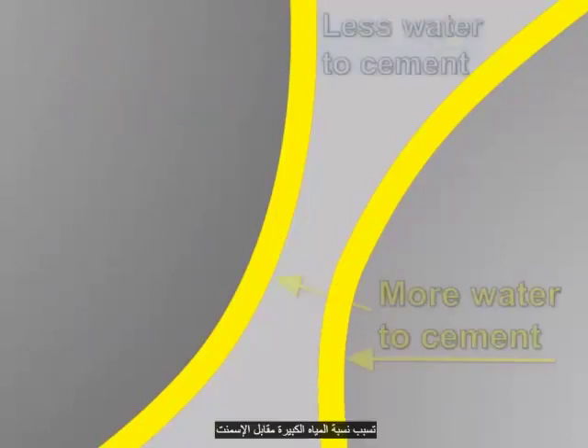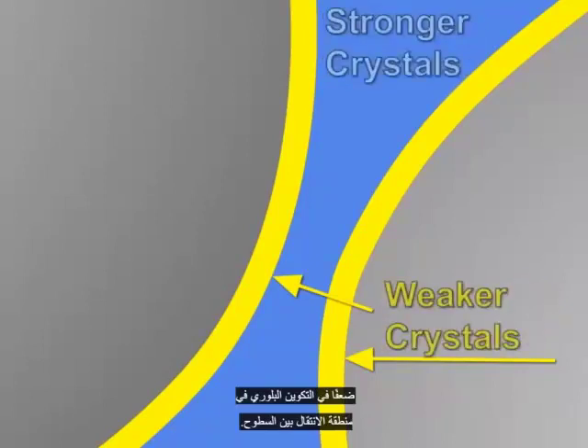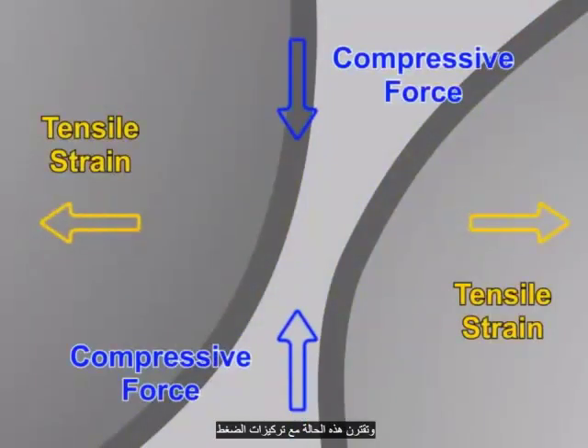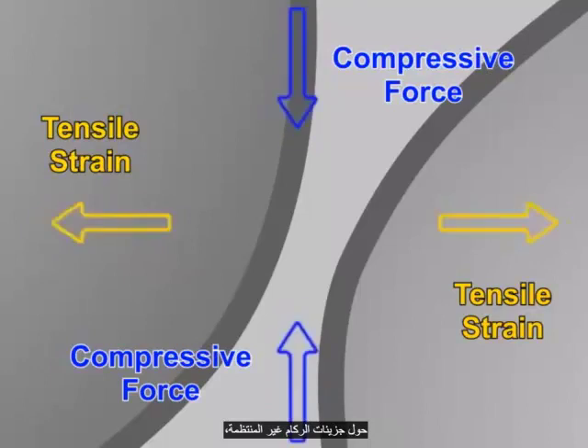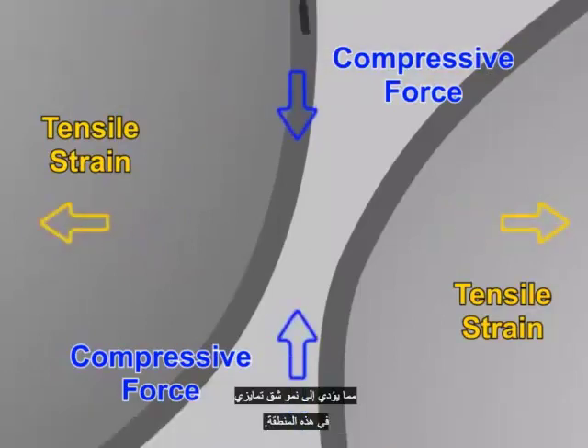The local larger water-to-cement ratio during mixing and hardening in the interface area results in a weaker crystal structure in the ITZ. This condition, coupled with the stress concentrations around the irregular aggregate particles, leads to preferential crack growth in this area.